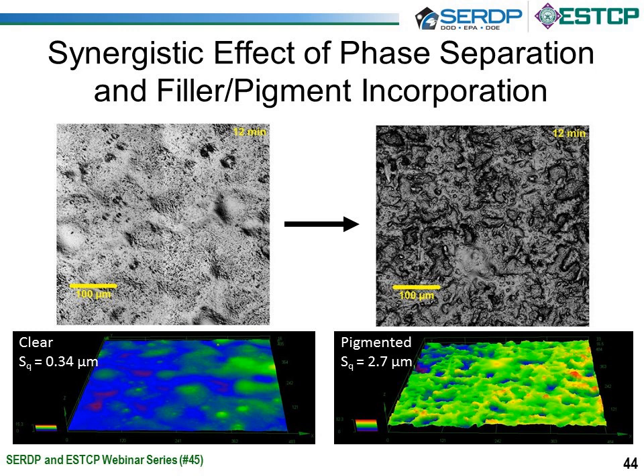We've demonstrated at this point the incompatibility of the polyols alone without the curative to form the domains. We've demonstrated that in clear systems we can cross-link them to result in rough textured systems, and now this illustrates that through the addition of pigments that we can even increase further the roughness of the coating system and result in a lower gloss system. Slide 45,